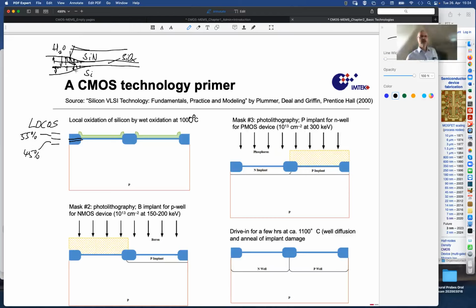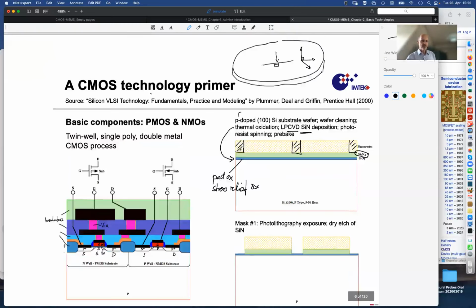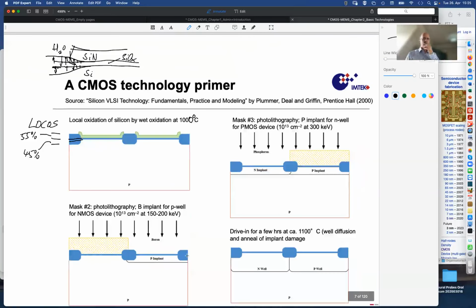And this structure is called the bird's beak, Vogelschnabel, in the technology jargon. Like a bird's head, and then there is a beak, very fine. So this has now elaborated a thick oxide, and you see where this thick oxide is used. You see here these thick oxide structures, thick insulator structures, that let you now run some metallizations over the silicon chip without contacting the silicon or having leakage currents and so on. The region with the thick thermal oxide is called the field. So this oxide is called the field oxide.